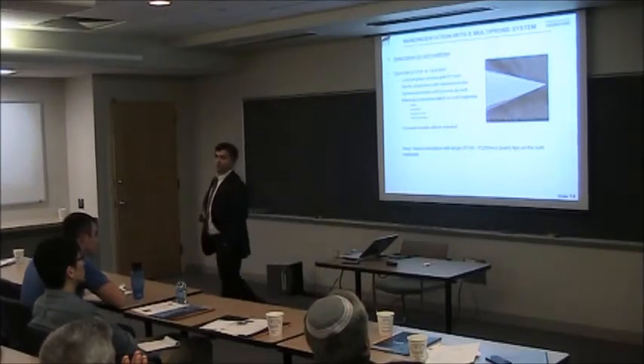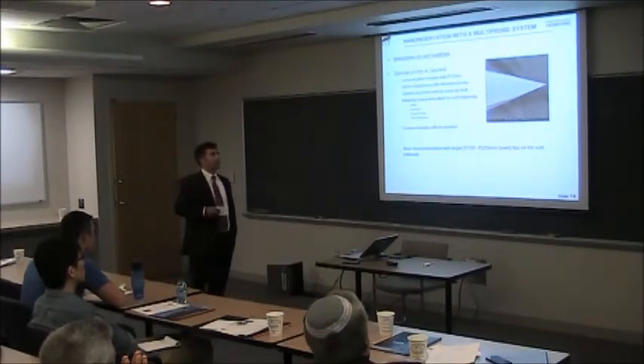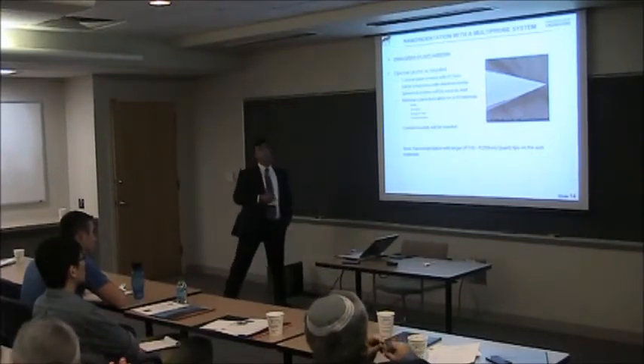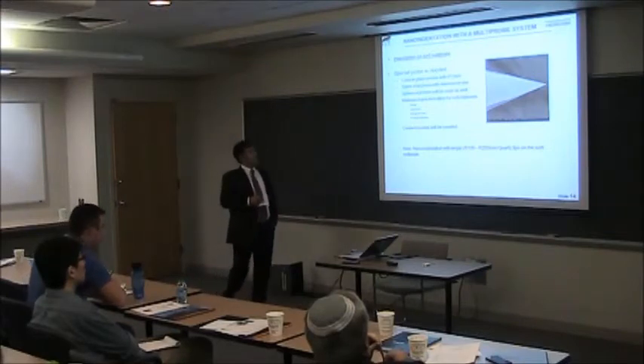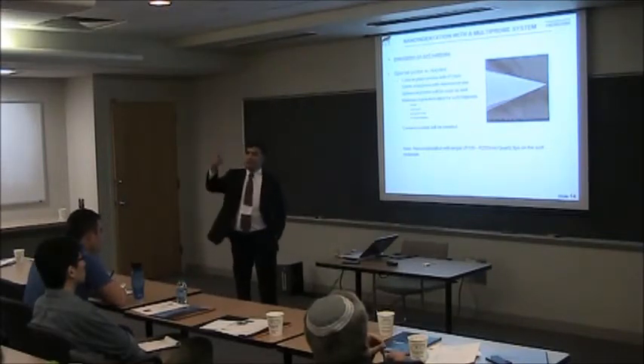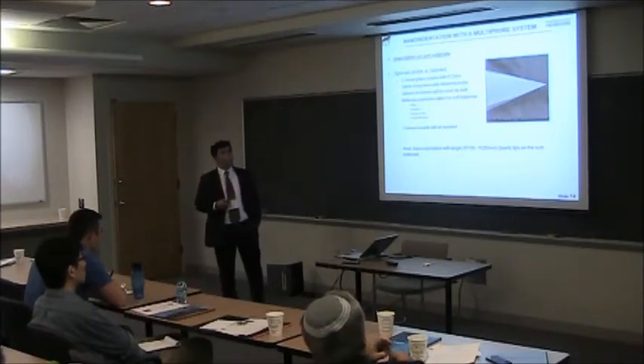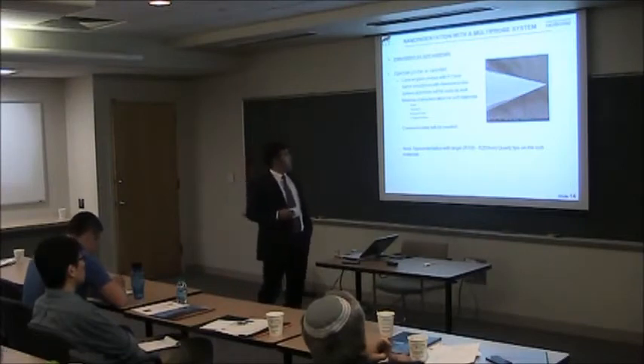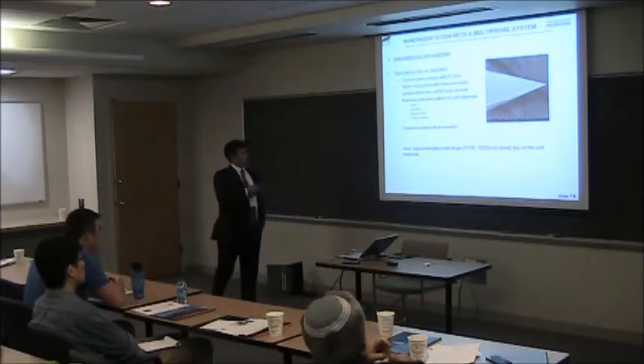Then we went to soft materials, which we really wanted to do because we want to analyze, or at least find out how we can accurately measure, the Young's modulus of the PDMS. So we couldn't use diamond because diamond would just go through the PDMS. So we wanted to use conical glass probes, just like Kit used, and his was a 20 nanometer tip. Ours is 15 nanometer.